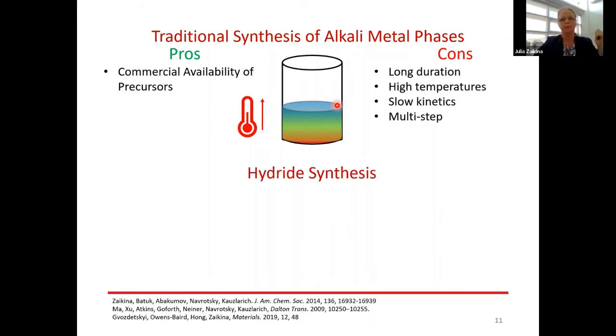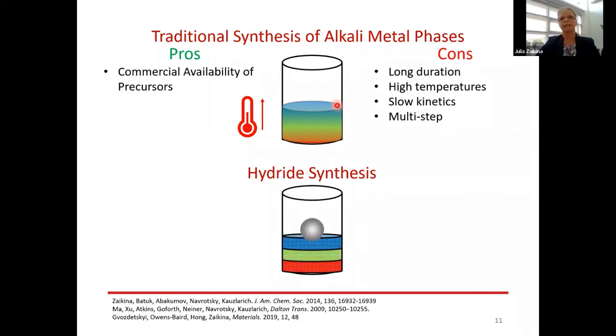So in my lab, we switched from using elemental alkali metals to their hydrides. And hydrides come as powdery material, which resembles table salt. Of course, they are very air sensitive, so we handle them in the argon-filled glove box. But nevertheless, they are powdery, so they can be mixed well by the technique called ball milling with the rest of the precursors. So this way, we already start with a very homogeneous reaction mixture, so we really don't need to go to very high temperatures,